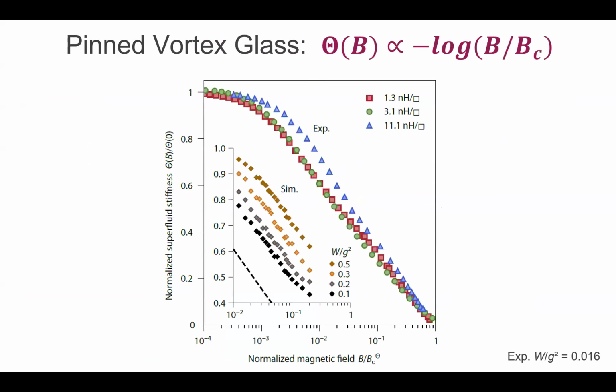And their simulation leads to this evolution of the superfluid density, which is also logarithmic and goes as a function of the disorder parameter. So the data are here. You see, if you cast all this data on this scale, it would end up here. If they would be able to go to lower, stronger interaction, they may reach our limit, but you see that it's totally consistent. There is a logarithmic suppression of superfluid density in this superconductor. Okay, good. A few minutes, and I go to the consequences of that.